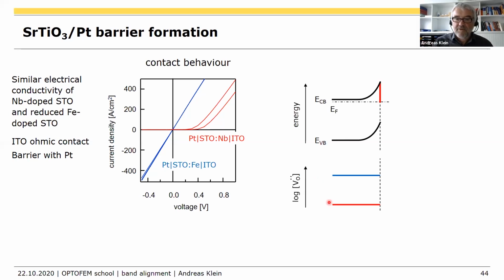Okay, so what happens? So that's our barrier with the platinum, and that's our oxygen vacancy concentration. In the iron doped strontium titanate, this is high. This is a logarithmic scale. In the niobium doped strontium titanate, there should be almost no oxygen vacancies, much less than here. If you equilibrate that, because you have a potential barrier here, the concentration of the oxygen vacancy will follow the potential. Electrons are here depleted. That means negative charges are depleted in the space charge region. And that means positive charges like oxygen vacancies would be accumulated. So after equilibration, you see that the oxygen vacancy concentration at the interface is enhanced.